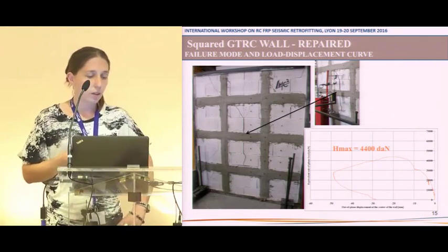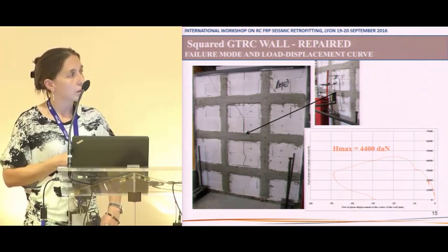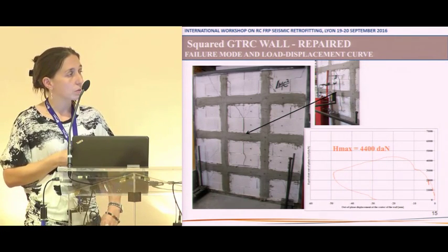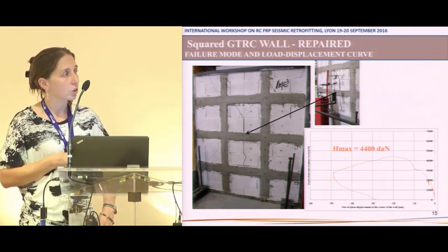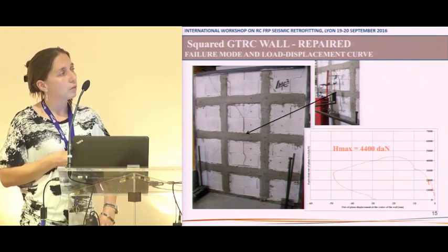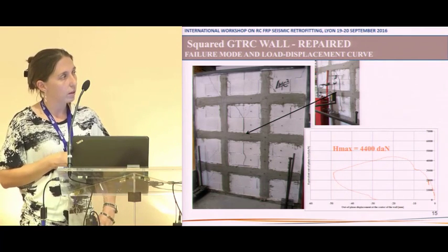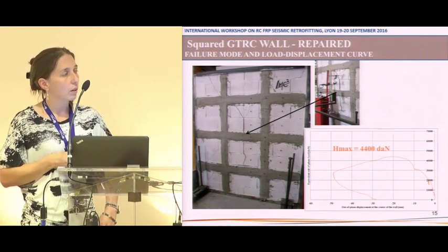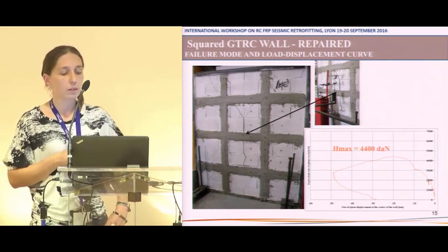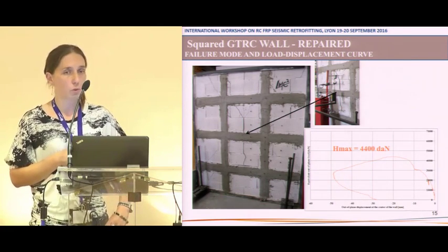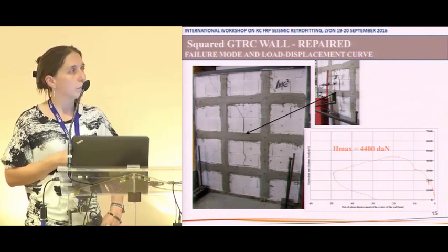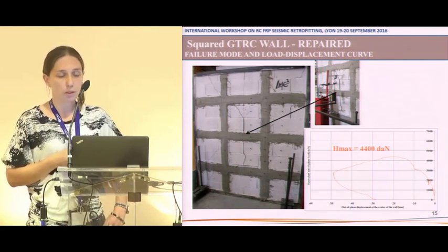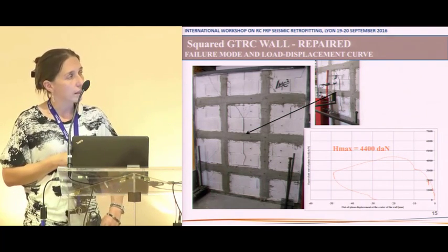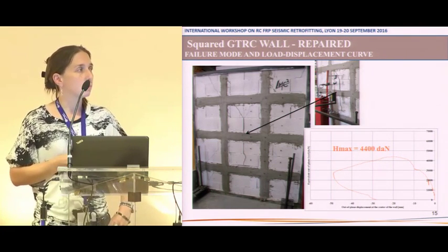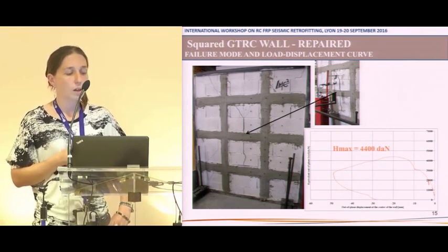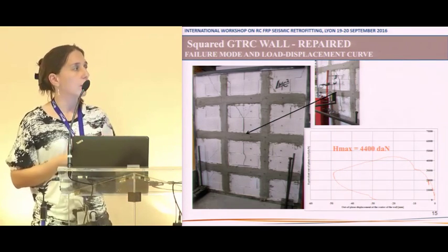For the repaired wall, we have the previous crack pattern with the vertical crack, and more inclined cracks appear, but we have the same maximum load as in the reinforced wall. That is to say, we have the same efficiency for the repaired wall as for the reinforced one. In that case, we have only some delamination and debonding, where the cracks have a very large opening.